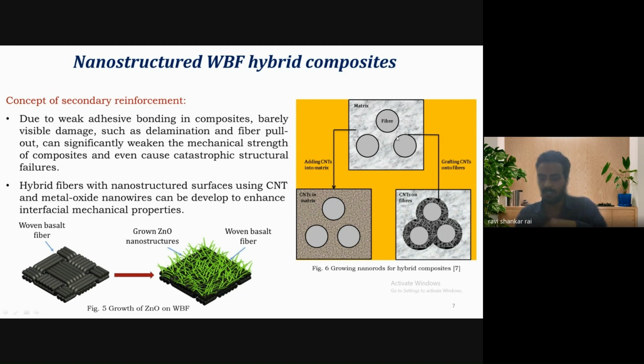Along with that, the polymer is mixed with the hardener, so it has a certain duration to mix, because after a certain duration it will start making bonds and start solidifying. So we have a limited duration for that. And also if we mix the polymer vigorously, there are chances of air entrapment inside the system, so there are chances of porosity. In the other method that we have developed, there is a grafting of the nanostructure directly onto the fiber. We have grown the nanostructure on the surface of the woven basalt fiber using the hydrothermal method.